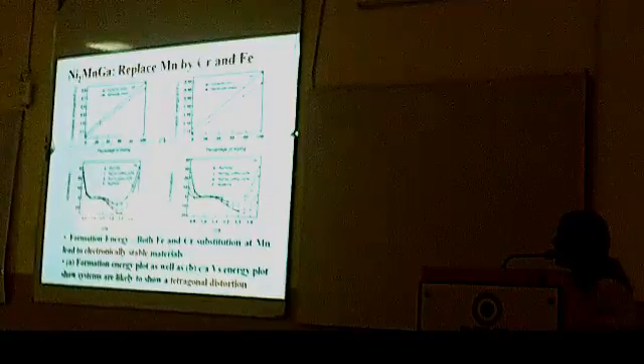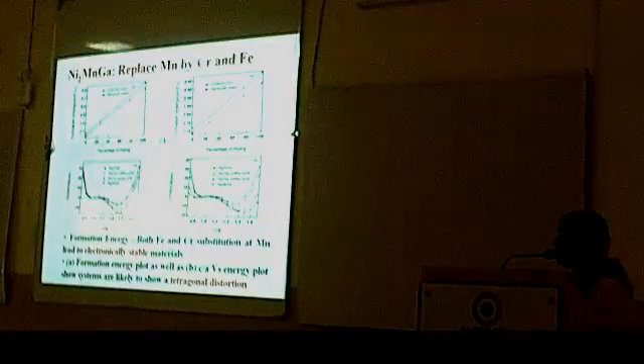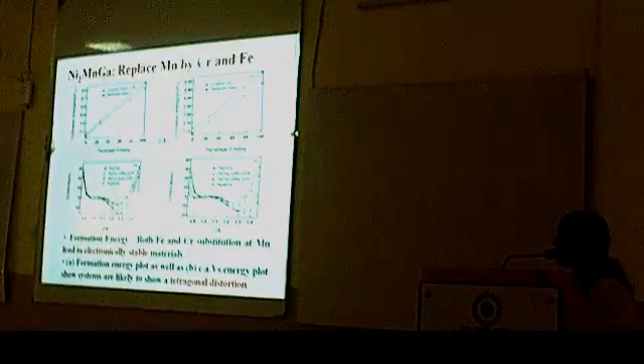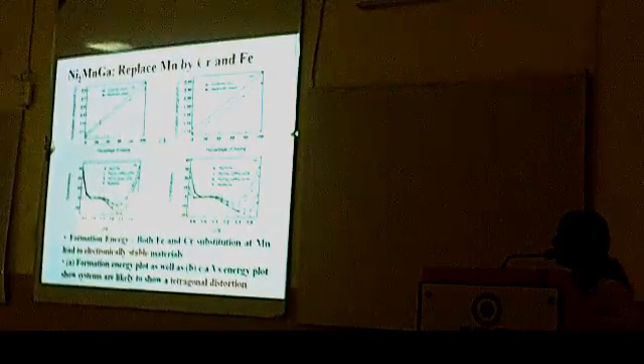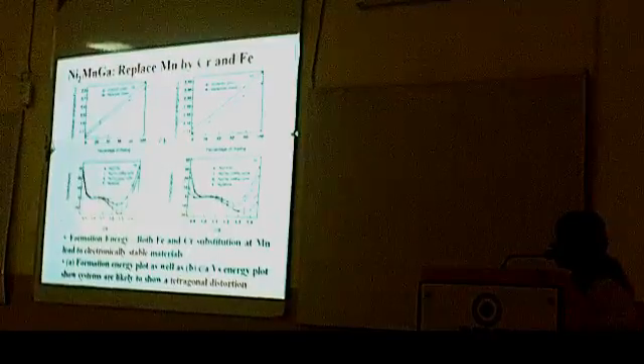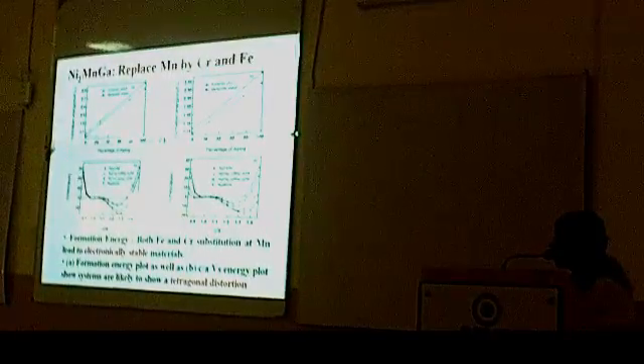So for percentage of substitution, both for austenite and martensite phase, we are plotting the formation energy. From here we see that the martensite phase is lower throughout the substitution - martensite phase has lower formation energy, as well as looking at the delta E. The austenite phase, the cubic phase, has been normalized - the total energies have been normalized with respect to cubic, so the cubic austenite phase has zero energy.